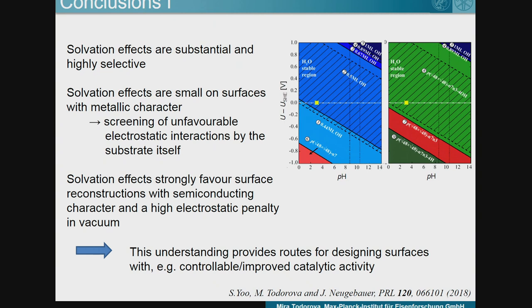And with this, we can draw some general conclusions regarding our modeling. In cases where we don't have metallic character and where electrostatics are important at the surfaces, considering the solvent will be important, and we are actually making a big error if we do not consider it. In metallic systems, where electrostatic interactions may play a less important role and where screening is also mediated by the substrate itself, if we neglect the solvent, we are making a lesser error. So for thermodynamic considerations, we can probably work with just one or two water layers, though of course it will be better to do the full calculation.